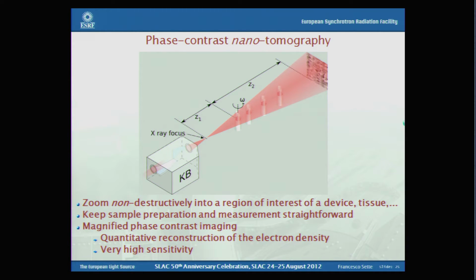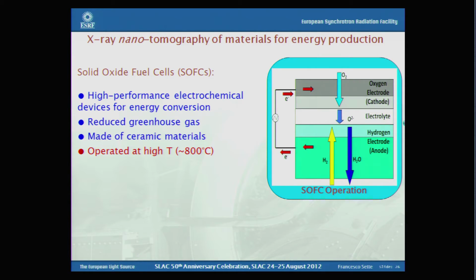I want to continue to show a more complete example in which you are able to do, using phase contrast, nanotomography, so a three-dimensional reconstruction of objects with nanometric resolution. And this is using this technique of zoom nanotomography on objects which are off focus. This allows you to keep the sample preparation very straightforward. And the magnified phase contrast imaging allows you quantitative reconstruction of electron density and also gives you very high sensitivity. And this has been applied to a solid oxide fuel cell.